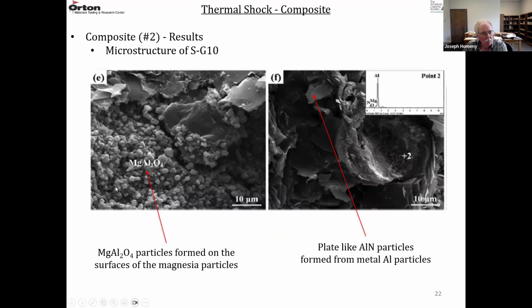And this more clearly shows the spinel particles. Again, spinel is MgAl2O4. These spinel particles are forming on the surfaces of a MgO particle. And this is a 10 micron bar, so these are pretty high magnifications. You can also see some aluminum nitride platelets forming. And again, this is the EDS analysis showing that these plates are aluminum and nitrogen.